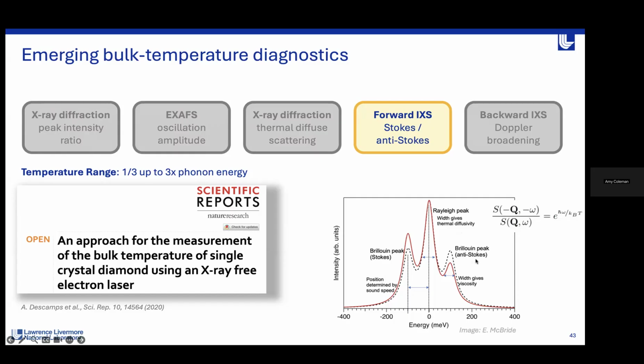At finite temperature, phonon creation and annihilation aren't equally probable, and by fitting the ratio of these peaks, we can pull out a temperature. The nice thing about this is it is not model dependent, so we don't need an EOS or a Debye assumption.